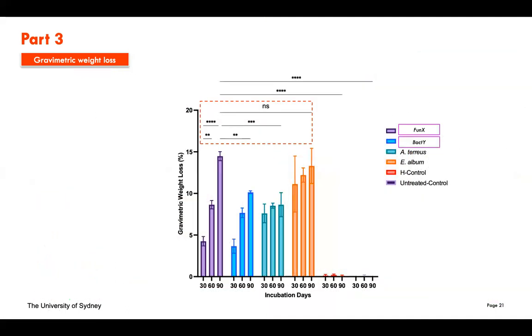So this is just a simplified version. I just want to show the weight loss only. When we compare the new isolates with the previous fungi, the Aspergillus and Engyodontium album, you can see that the new fungal isolate produces the highest weight loss compared to the previous fungus. It also shows a much higher degradation rate and weight loss compared to the bacterial isolate. But this comparison is only for the heat-treated film. I just want you to see the differences at one go.